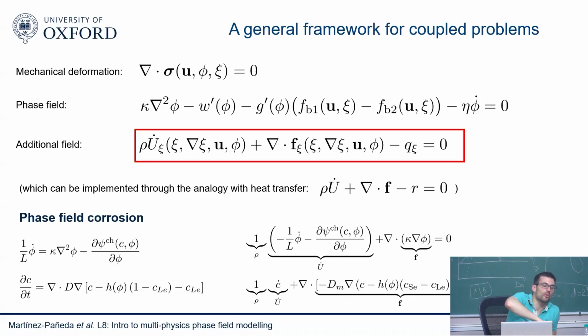But for example, when we look at stress corrosion cracking, where we have both material dissolution and fracture, material rupture, then we have two phase fields, the fracture one and the corrosion one. Both can be built in this phase field analogy, and as I will explain in a minute, we can solve as many of these additional equations as we want in Abaqus with a trick that we have now. So this could be done for multiple phase fields as well.